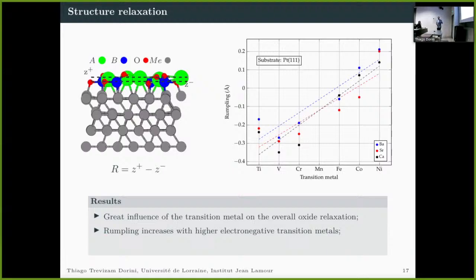To begin with, in the structural relaxation for all these systems, we have seen that there's a great influence, especially of the transition metal, in the overall oxide relaxation. Here I would like to highlight the first property, the rumpling, which is given by this equation, the difference in height between the cations and anions in the oxide. And as you can see, when we increase the electronegativity of the transition metal, there's also an increase of this rumpling parameter.